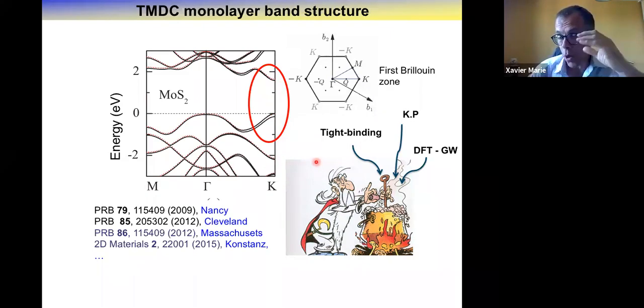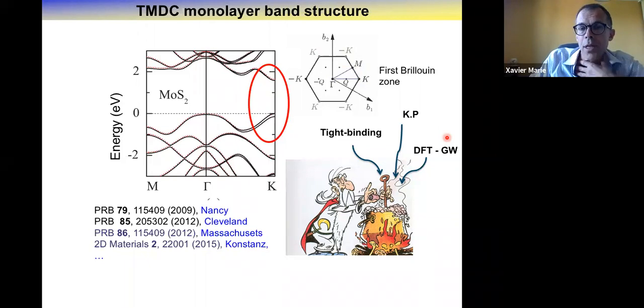So if you are used to optoelectronics, III-V semiconductors, II-VI semiconductors, it's very different, because in these very well-known materials for optoelectronics, usually we deal with optical transition with electron and hole which lie in the center of the Brillouin zone, in gamma. Whereas here, we will deal with optical transition where the electron and hole states involved in the optical transition lie at the edges of the Brillouin zone. So this will really change the symmetry and will have very interesting properties.